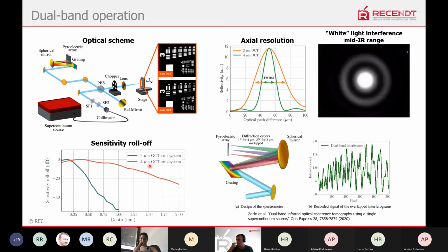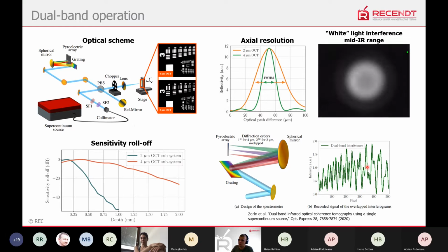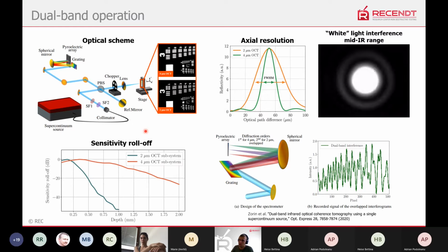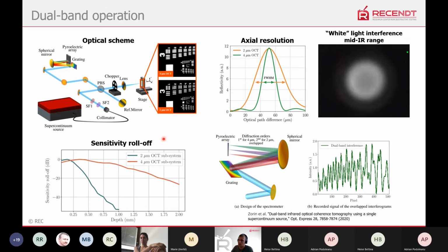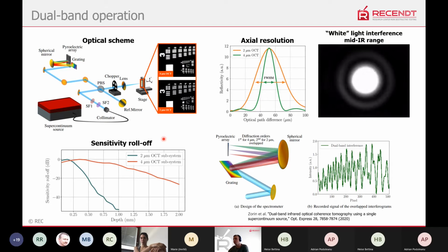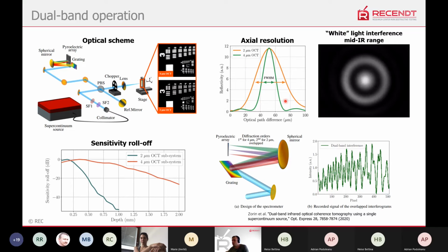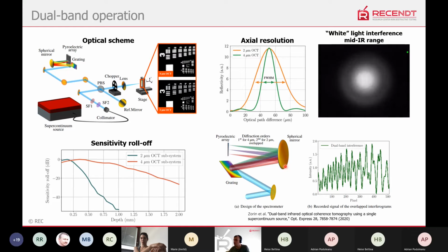And some optics was replaced at this point so that it's optimized for both ranges more or less, and then I could suddenly see such effects that I see both interferences, that we have interference at 4 and interference at 2. And then by inserting some spectral filters, we can get imaging at 4 and at 2 using the same source and the same system. Of course, at 2 microns, the resolution would be better. I think this is very clear.